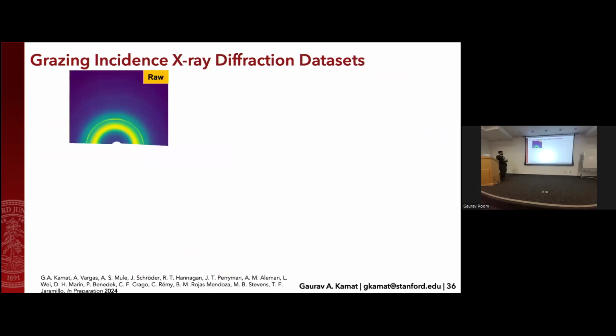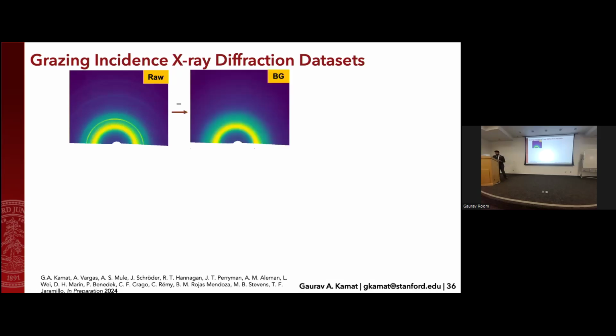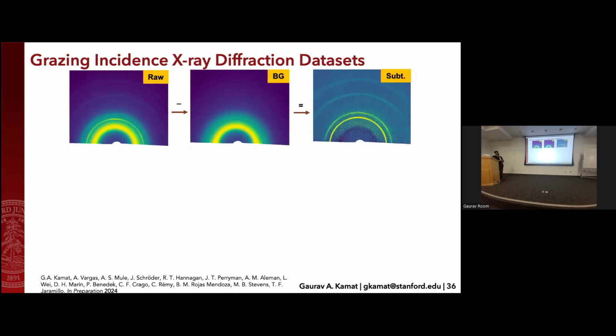Now, in terms of what this data looks like on the 2D detector, it generates an image, and that image looks something like this when you take it raw. You'll see some very well-defined rings, but there's also this big diffuse ring. That diffuse ring is just due to solvent scattering. You have water and anions in your system that are scattering your X-rays. So you need to collect a background, which shows you your diffuse ring. When you subtract those, you get a really nice picture of the diffraction rings of your material specifically.